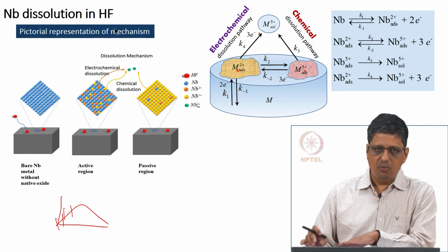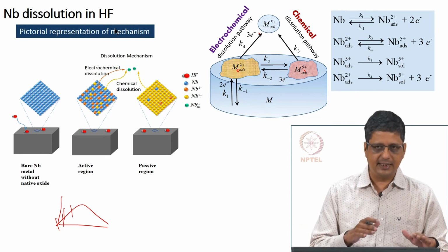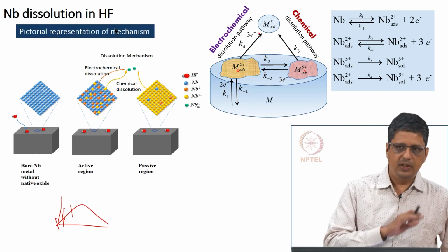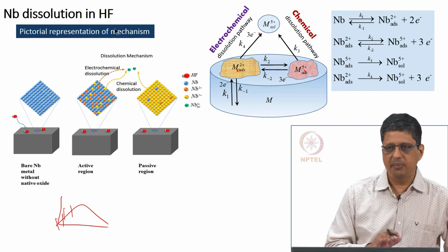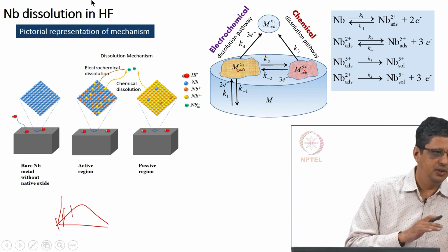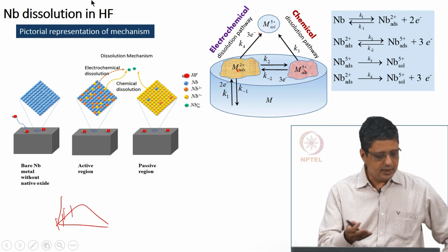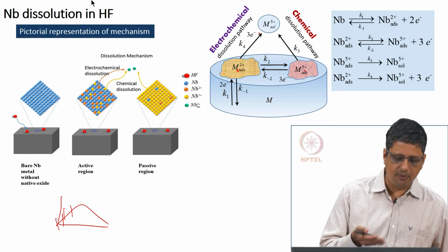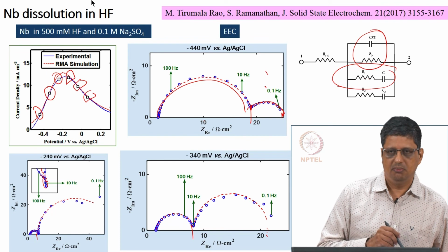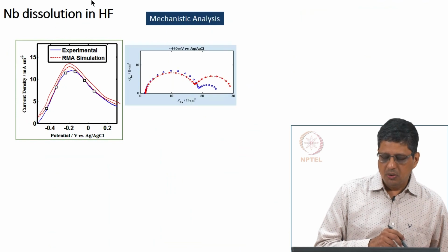Some of the niobium would have converted to suboxide, but net if you look at it now versus a few seconds later, on the average I will say maybe 95% will be pentoxide, 3% may be suboxide and 2% may be niobium. I do not mean to say the locations remain the same, I mean to say the surface coverage when I look at it on the average is going to remain the same under steady state condition. And this gives you, I think, a better idea of what is happening compared to saying these are the element values here, although the fit is better in that situation. Okay, we will stop here now.